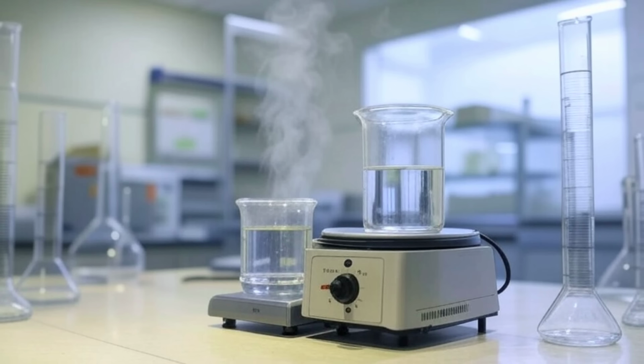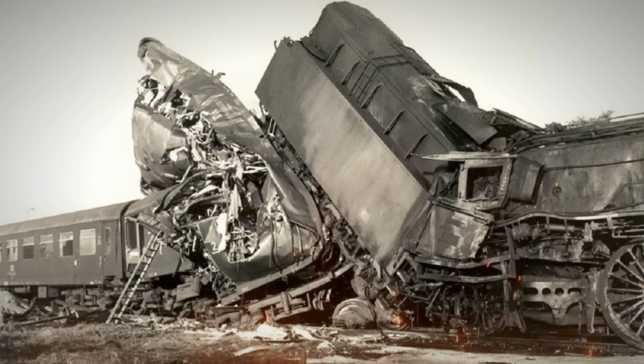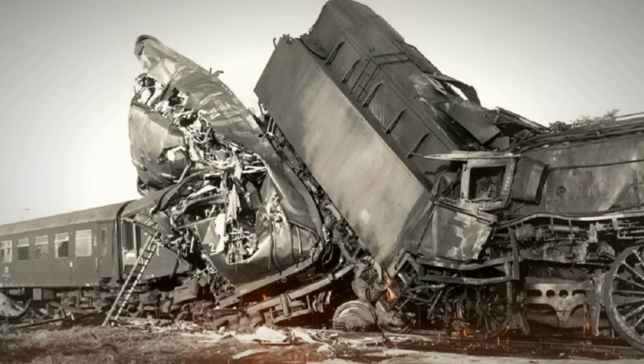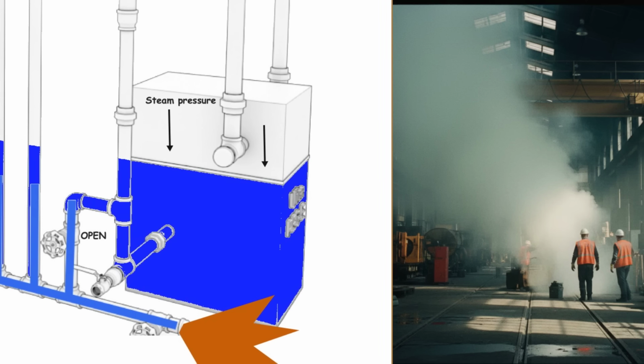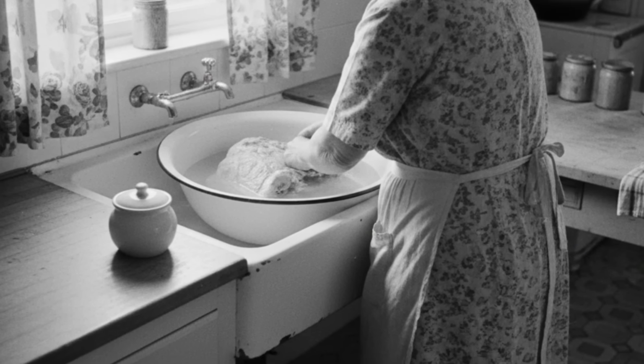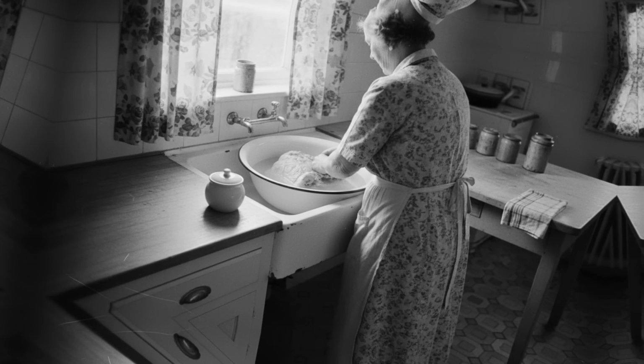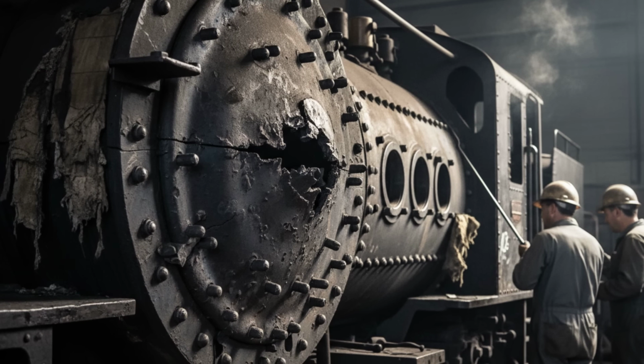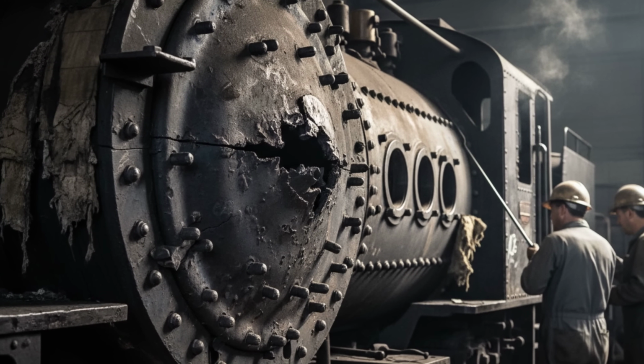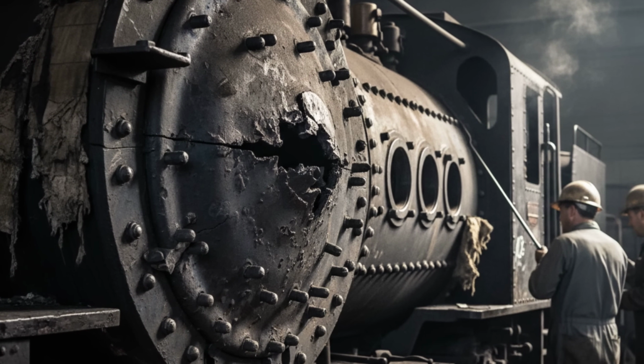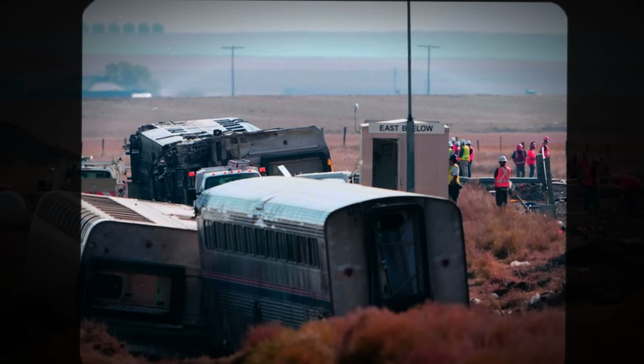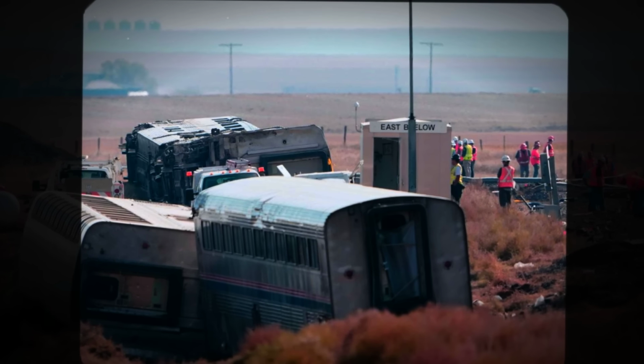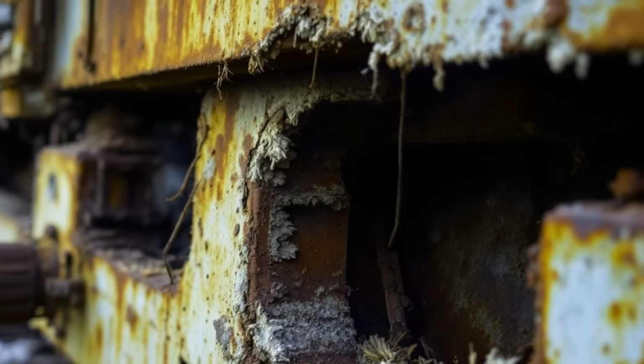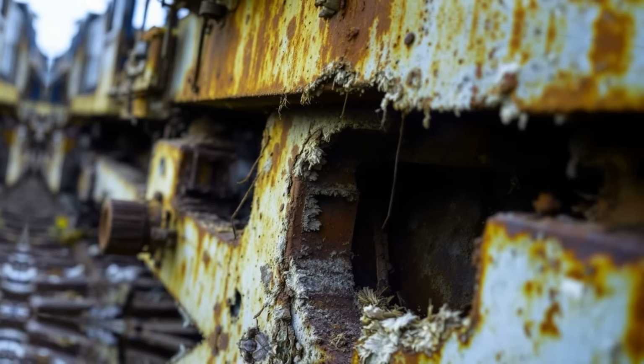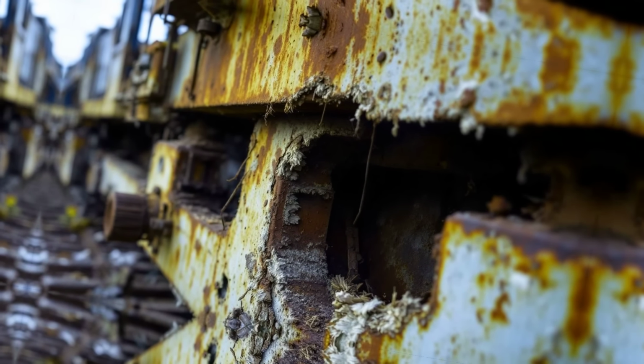Flash vaporization did the rest. Superheated water, now in contact with the firebox atmosphere, expanded at over 200 times its liquid volume. The result was a kinetic shockwave that tore the front crown sheet downward, bulging it a full foot over 60 stays and ripping a 6-inch gash near the tube sheet. The Federal Railroad Administration investigation reads like a post-mortem from a century earlier: scale in the sight glass, missed maintenance intervals, a crew unprepared for the old rules. The report's language is blunt.